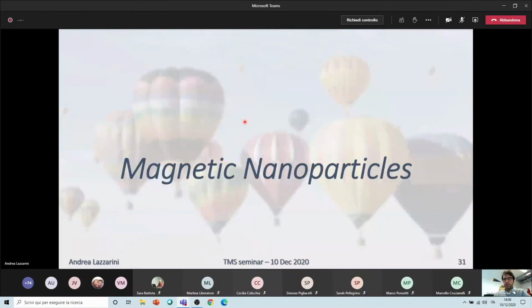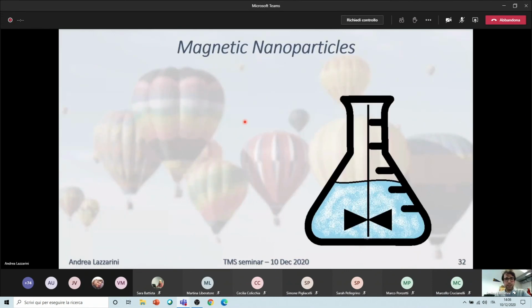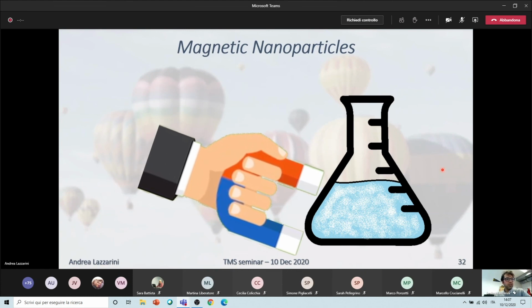And now, just a few words about magnetic nanoparticle systems. I will be very quick on this part, since it's still under development. So we were making nanoparticles that can be magnetically recovered. This means that when you have a reaction environment and you stop the magnetic stirring, and you go close with the magnet, you wait some minutes, and basically you can recover your catalyst in this way. So you can remove the liquid phase, without even removing the catalyst from the vial where you are performing your reaction, and it's already ready for the next cycle.